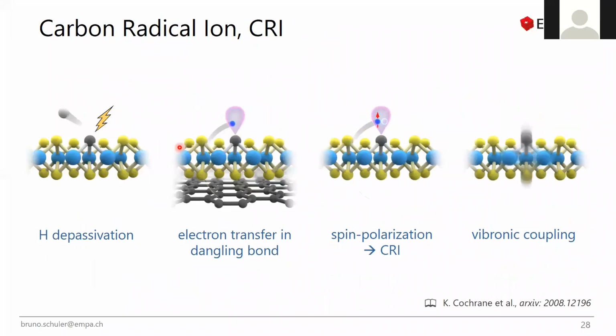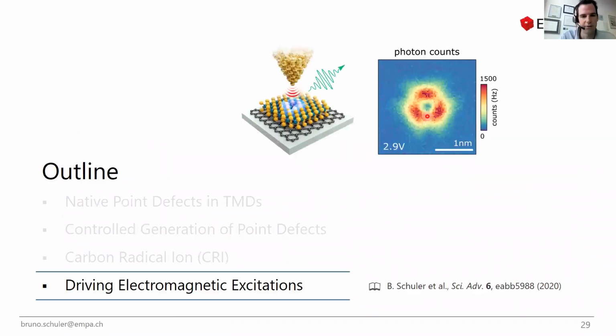Okay, so this should summarize this part. We can do a selective hydrogen depassivation with our scanning probe tip, then have this dangling bond singly occupied, as the graphene donates an electron to this dangling bond. It becomes spin polarized, and we also studied in detail the vibronic coupling at this defect.